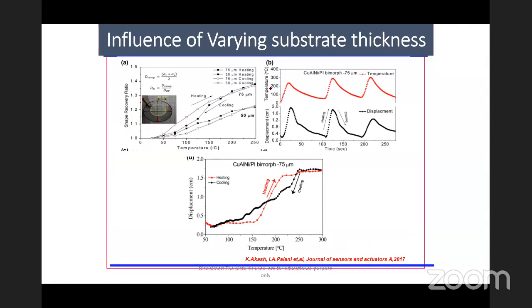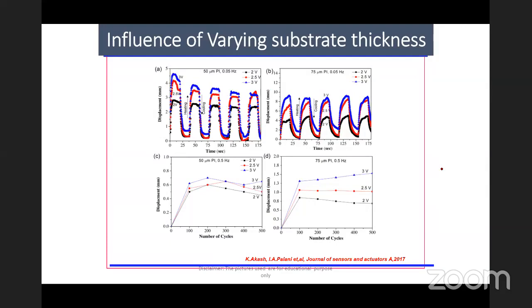So we have plotted with respect to temperature-time, and with respect to displacement-time. As far as temperature-time is concerned, this is your heating cycle and this is your cooling cycle. During your heating cycle, you get a higher displacement, and if I want to have control over the displacement, I can just cool it. And this is your hysteresis plot, which confirms the SMA behavior for an actuator. So, we did a detailed life cycle analysis.